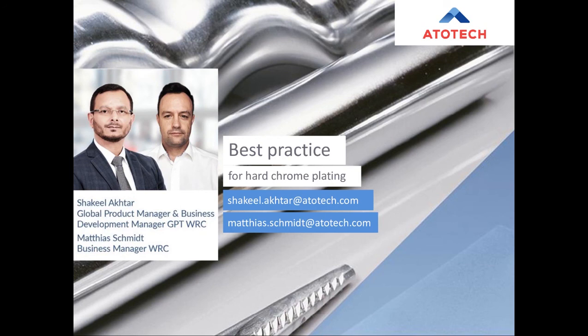Typically on platinized titanium anodes, you can have some layer formations. Basically, when they're without current in the chrome bath, the cleaning works very well. But of course, they can also be removed with rinses and can be treated with some mild acids. In any case, it's not recommended to use any kind of abrasive cleaning, like with brushes or anything like that, because this will definitely destroy the platinum layer and will destroy the anodes.